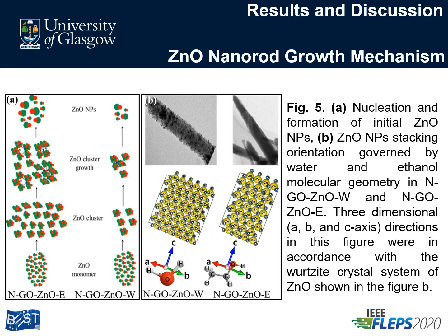As zinc and oxygen atoms of zinc oxide are forming consecutive layer structure, these interactions among a growing crystal surface will act as a substrate for the next layer of zinc oxide. The extent of these interactions along C-axis will determine the length of the zinc oxide nanorods, while the interactions along M-plane will define the width of zinc oxide nanorods, which we believe are dependent on the geometry of the solvent molecule.